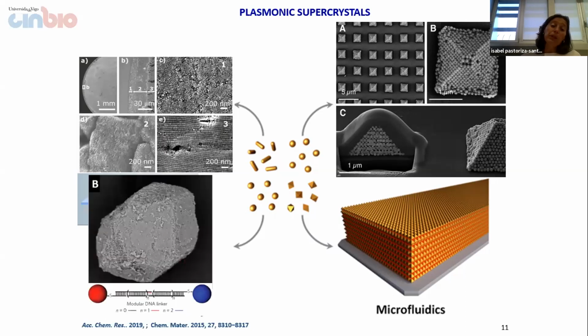Another technology or methodology to obtain supercrystals, also reported in the literature, is related with the assembly of the nanoparticles in a colloidal dispersion. In that case, the assembly is induced by the ligands that are at the nanoparticle surface. For instance, this example here is the case of the assembly induced by complementary DNA strands.